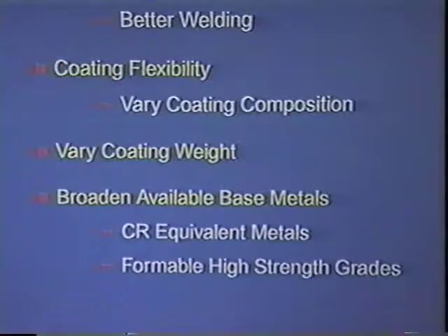Vary coating weight, electrogalvanize, just like EG. You can decide if you want 60 grams on top, 30 grams on the bottom, or whatever combinations you want. The advantage of electrogalvanize is you can do a one-sided coating. And there used to be a big market for that where you just want one-sided zinc coating. And hot dip, you couldn't do that because it's coming through molten zinc. You're always going to have something on one side. Maybe you can blow real hard and get it as low as you can, but you're always going to have two sides zinc coated. So if you only wanted one side, then you'd need electrogalvanize.